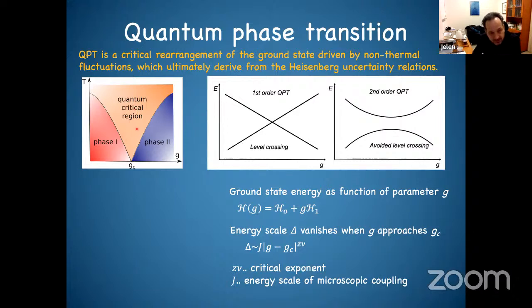And this quantum critical region is a special state, which is very difficult to describe, because now you have two competing schemes. You also have thermal fluctuation. So it means the system can jump from phase 1 to phase 2, and basically it's living in some new state. And indeed, all these strange metals and new materials which have been discovered, which are probably good candidates for high TC materials, it's believed that this new generation of high TC could be understood from this quantum criticality. And it shows very, very interesting material properties.